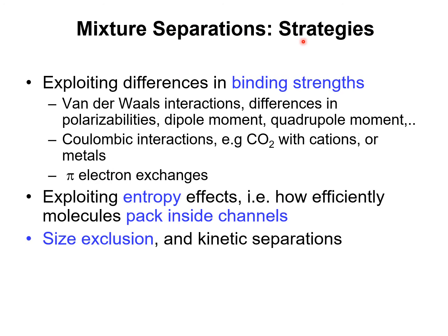There are basically three different strategies that can be employed to separate mixtures using microporous crystalline adsorbents. We could explore differences in the binding strengths, the binding strengths being dictated by van der Waals interactions, differences in polarizabilities, dipole moments, quadrupole moments, and Coulombic interactions.